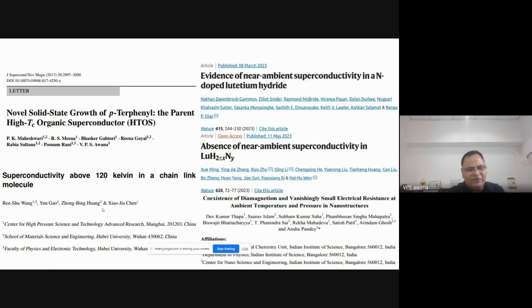There was a paper on 120 Kelvin in an organic molecule, carbon-based. When we synthesized this sample, p-terphenyl, it also failed. It did not show the 120 Kelvin TC. So on and off, this type of news was coming in the literature: this compound has this TC, that compound has that TC, and scientists have to run behind whether it is there or not. So besides iron-based and copper-based, there was no real news till date.